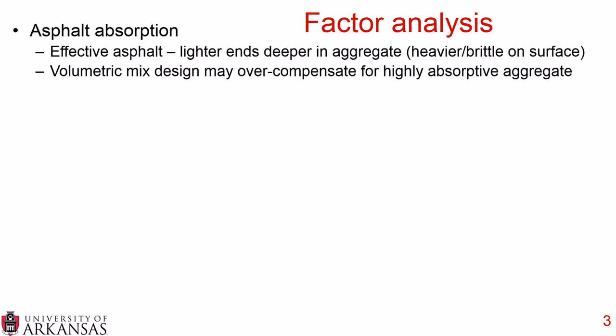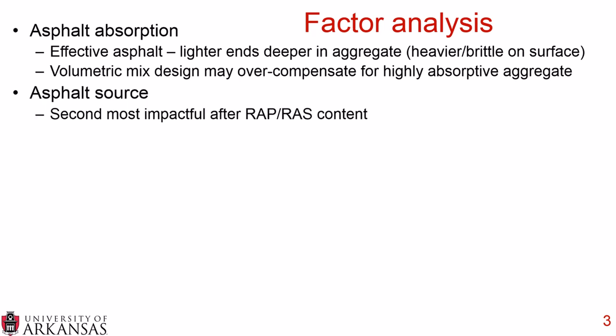In an analysis of the factors, they found that for asphalt absorption, the theory was that the effective asphalt, or the asphalt that's coating the aggregate, was actually a little different than the base asphalt because they thought that the lighter ends would go deeper into the aggregate, which would leave the heavier and more brittle asphalt binder components on the surface. However, they did find that the volumetric mix design may have overcompensated for these highly absorptive aggregates, so they didn't see that trend.